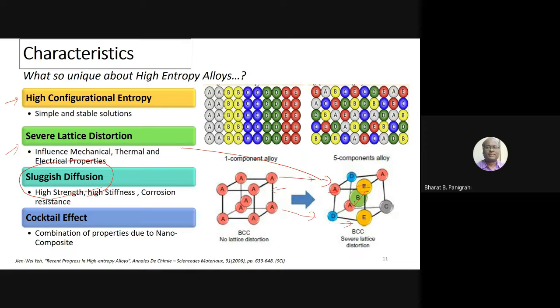And that leads people to believe that diffusion is very sluggish, meaning slow. Where diffusion is high, you may expect high grain growth. So that is the reason people believe this has very sluggish diffusion, which is good, because when your grain is growing, you are losing the property. You know, there is the Hall-Petch relation. Because of the Hall-Petch relation, you lose the property. When grain is growing, hardness and strength drop drastically. But if you are able to control or restrict the grain growth, you can retain the strength and hardness significantly. And that is the beauty of this high entropy alloy.